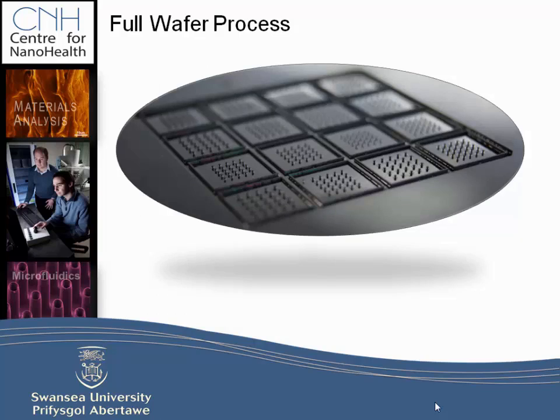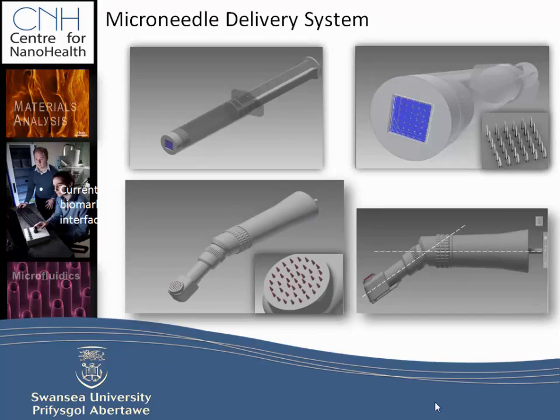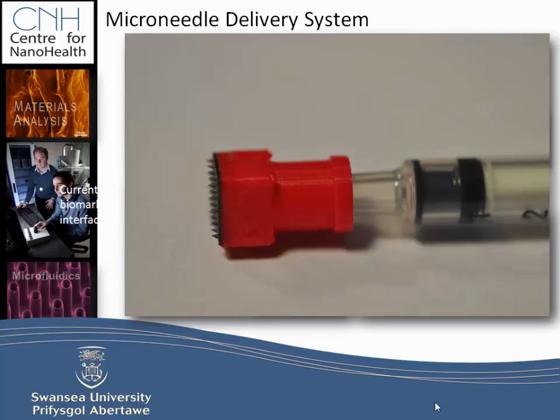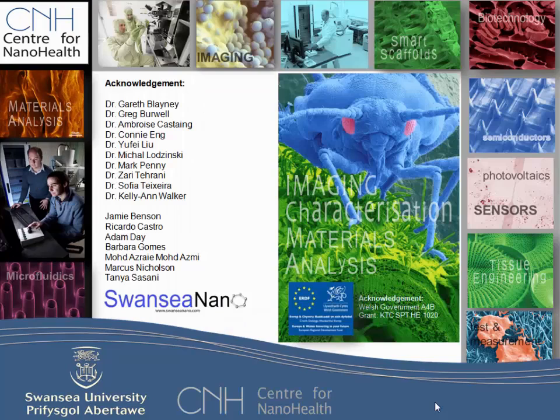There's a single chip, 10 by 10 millimeters. Still needs some optimization. So the spacing between the needles is very important. Otherwise, they act like a bed of nails and won't penetrate properly. And also the injection site. So where you inject on the body, so where your skin is thinner, obviously you need less pressure to penetrate the skin. So at the moment, we're optimizing different needles for bespoke applications in drug delivery, in sampling, and vaccine delivery. Simple applicator system, we stick that on the end of a syringe, and then we're able to either extract fluid or inject fluid through the skin.